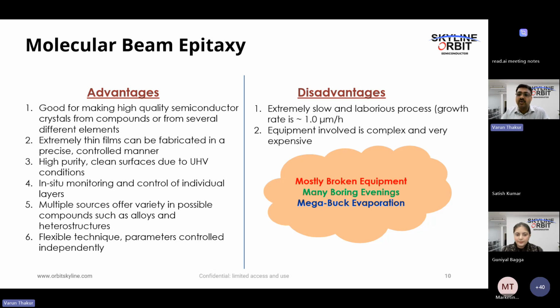You have precise control of the thickness of the layers. You can increase or decrease the mole fraction, so you can change the band gap. So for band gap engineering, it is very important. So it's a very versatile tool, and you have a lot of flexibility when you are making your film. So you can make them in a very precise, controlled manner, as much thickness as you want. The interface, because the shutter speed is very sharp, so very fast, you can make very precise interfaces. There will be no intermixing, and you can check that in TEM images where you can see atomically sharp interfaces.